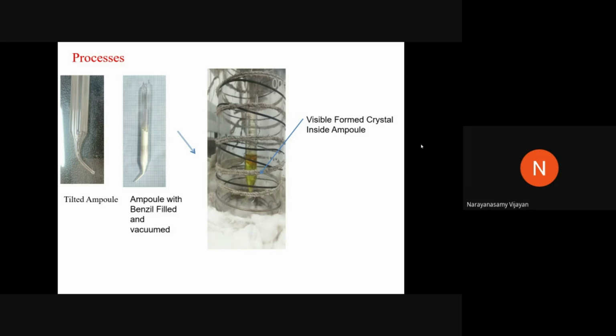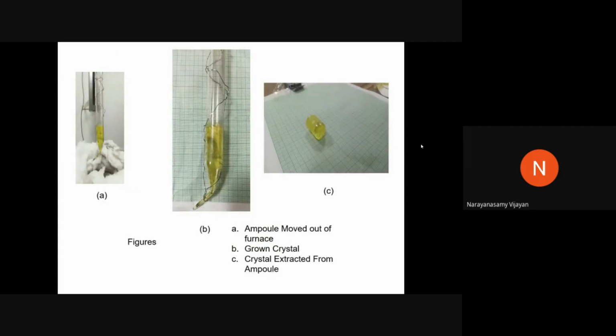You can see after the melting, inside it is an almost yellow colored liquid, that is the molten state. And whenever it goes down slowly in the bottom, we can find where solidification starts. Initially this material is in solid form, that is powder. Then after absorbing the heat it melts, then it goes for solidification: molten liquid form, then solid. That is the final single crystal form. After that, we can cut the crystal, and all are in the similar direction.